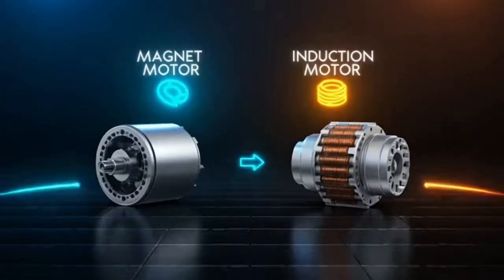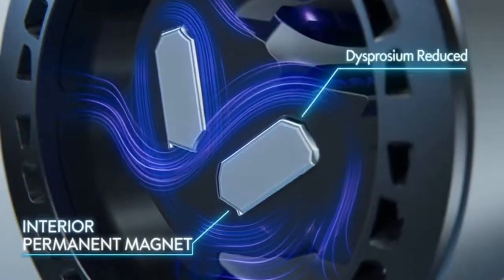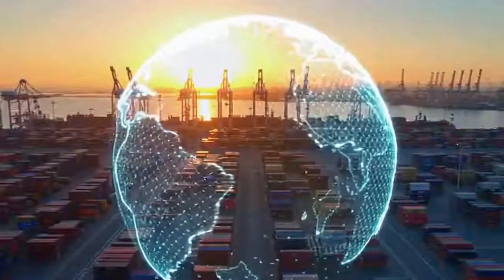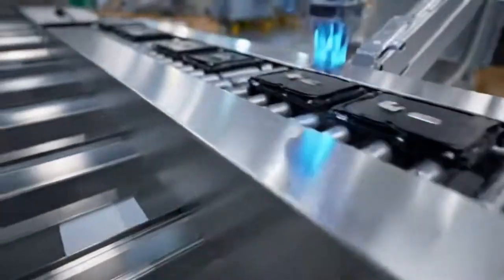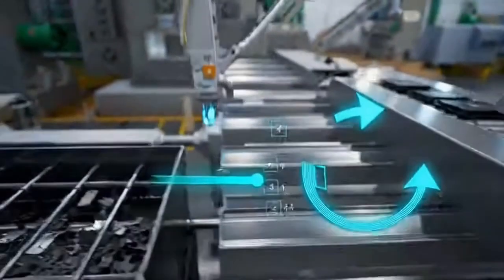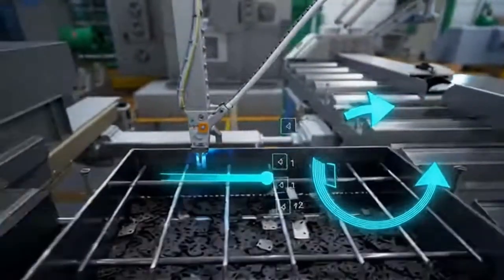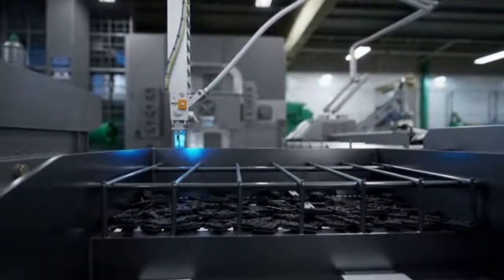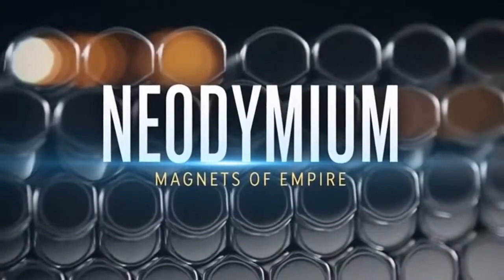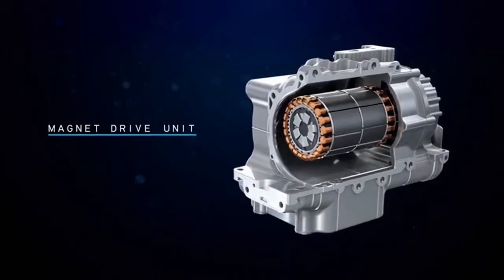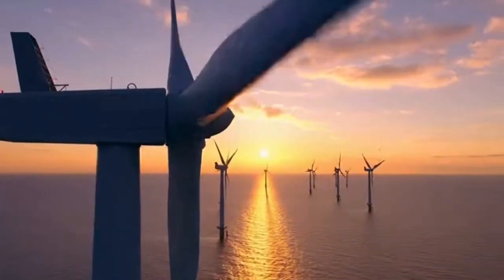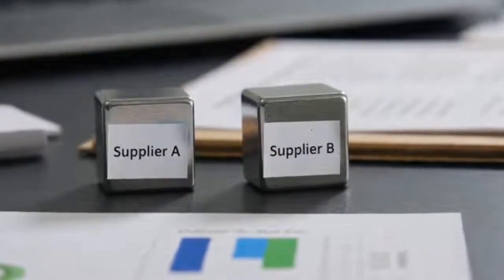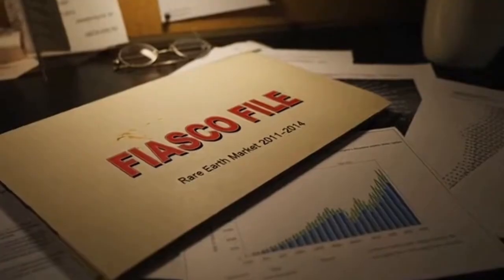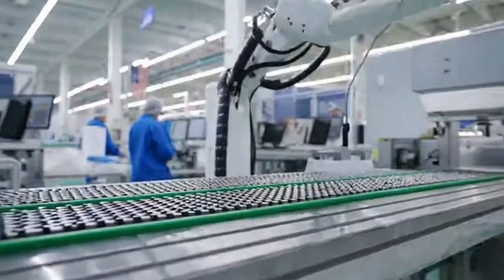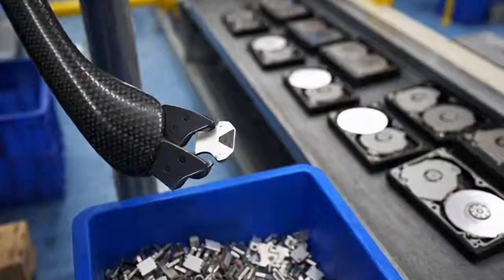And then come the tests that outsiders might consider paranoid, but which the people who design these things consider simply prudent. Thermal cycling. Bake it and freeze it repeatedly to see if any magnet or adhesive loses its nerve. Salt fog testing. Essentially spray a saline mist at the rotor for days or weeks to simulate years of exposure and make sure no little coating defect blossoms into full-blown corrosion. Vibration testing. Shake and spin that rotor until it has essentially sung its entire range of resonant frequencies and nothing has come loose or cracked. Only after all that do you test the motor as a whole.